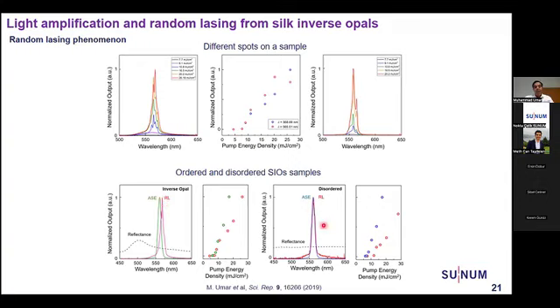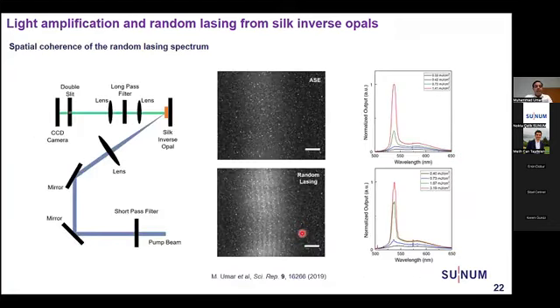And if we use a disordered structure by mixing different sizes of particles, we could also see random lasing. Then we confirm this lasing by using spatial coherence. We utilize a double slit, and when there was amplified spontaneous emission, we could not see any light in the form of fringes. So this means it is just amplified spontaneous emission. On the other side, when there are lasing peaks, we see this spatial coherence phenomenon. Spatial coherence is a basic phenomenon to check whether the light is coherent or not. So this means our light is coherent. So this was the random lasing from the silk inverse opal.